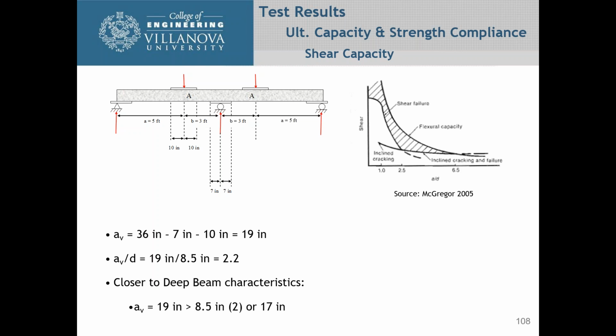So that's if you look at what the point load is. But now if we actually take into account that these plates were 20 inches wide, this plate was 20 inches wide, this plate was 17 inches wide. So now your distance is 36 inches, which is the distance from here to here, minus the 7 inches, minus the 10 inches, which is 19 inches. So now you start seeing that the load, this is a very stiff plate distributing this load, and this is a stiff plate. This is the distance. And so, you know what? Now we're looking at it being acting more like a deep beam.